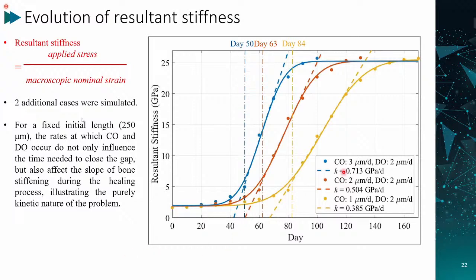We can see for this CO and DO, CO faster than DO, only 50 days to close the gap. But if they are at the same rate, it takes a longer time. If the CO is slower than the DO progress, we need 84 days to close the gap. But also these kinetics affect the slope of bone stiffening, which means the slope here, during the healing process, illustrating the purely kinetic nature of this problem.